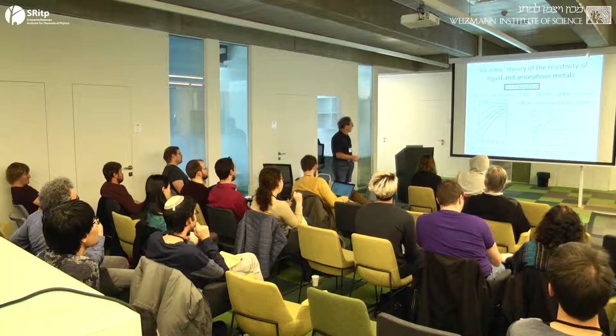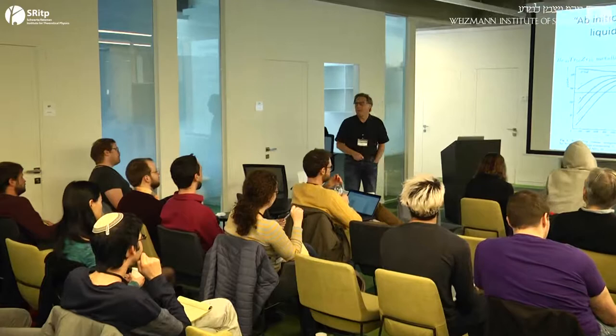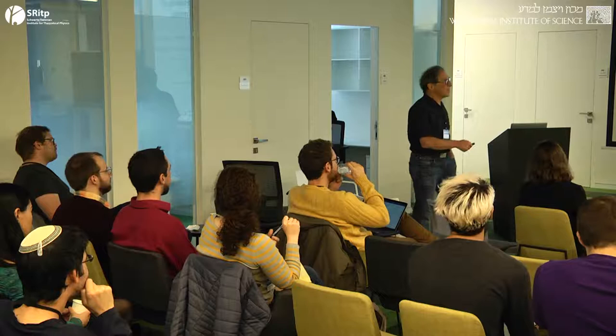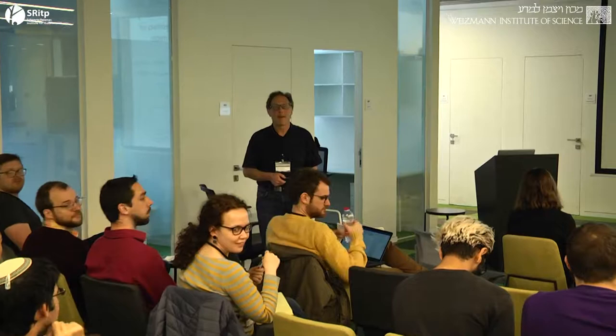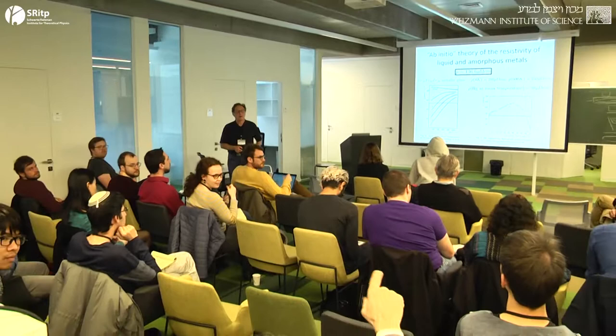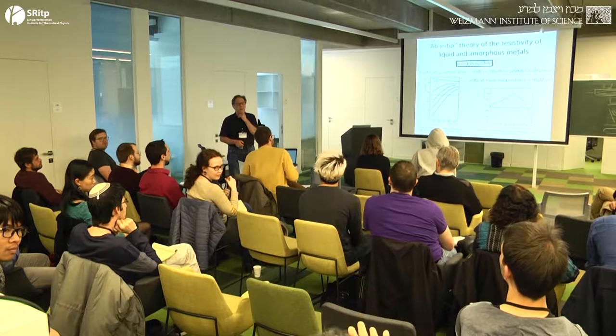And I challenge you to find any material that satisfies that criterion that isn't going to have a resistivity within roughly a factor of two of what I've calculated. If you do, I think that's very interesting. Yeah. I completely agree with you, but I think you should add one important thing. These are materials which have one electron per atom. In that case, the distance between atoms and the Fermi wavelength are of the same order of magnitude.